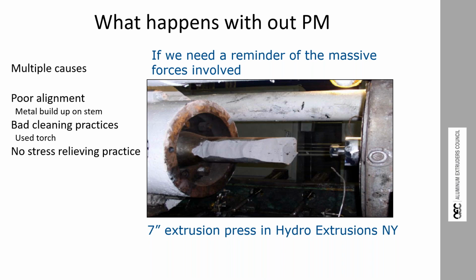Unfortunately, the torch rested for a little too long in a few spots and softened the steel. There was no stress relieving practice for the stem, and so over a period of time, a crack grew. And that in itself wouldn't have been too bad because we could have seen the crack, like the picture that Danny showed you, except that we still had the poor alignment of the stem and the container. And that meant there was aluminum smeared all down the side. The aluminum was smeared in the same place that it was smeared before, so the same place where the torch had been, and that aluminum hid the crack. So the first thing the crew knew was bang, and pieces of hot steel flying in all directions.